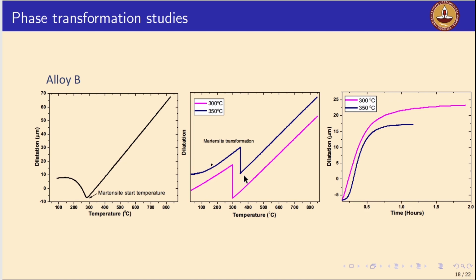So if you look at the alloy B chemistry, we hit a jackpot, right? Here we can identify the MS temperatures again, and we have to make sure that the bainitic holding is above the MS temperature. We also did that. If you look at the case of 300, where the bainitic holding was at 300 degrees centigrade, when we cool back to room temperature, there is no martensite formation. So that's very nice, isn't it? And if you look at the actual transformation, we could achieve the complete bainite transformation in about an hour. So it's reasonable, right?